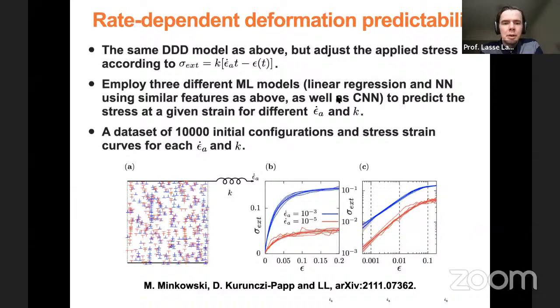And we now try to predict the stress at a given strain for different values of these driving parameters, so the strain rate and then this stiffness parameter. So for this specific study, what we did was we generated 10,000 initial configurations to correspond to a stress-strain curve for each of these values of the strain rate and the stiffness parameter.